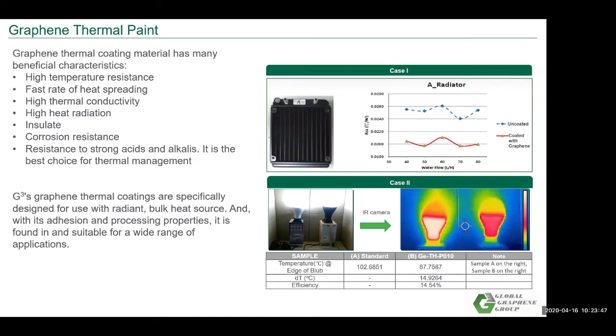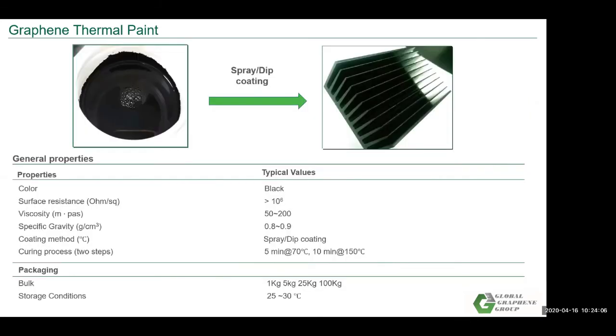It's about 14 degrees C difference. And I think people know the importance of temperature for LED life. So with 10 degree C of difference, LED life can probably double. So graphene is very effective on this. And as I just mentioned, you can simply use spray coating or dip coating techniques to put it onto your surfaces or heat sinks. And we can also offer different quantities.